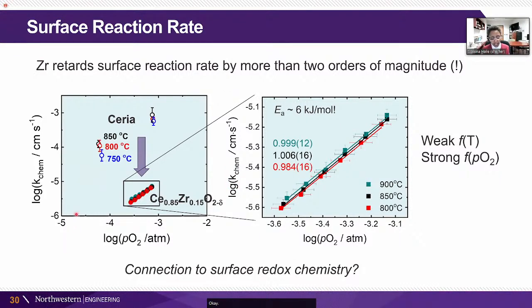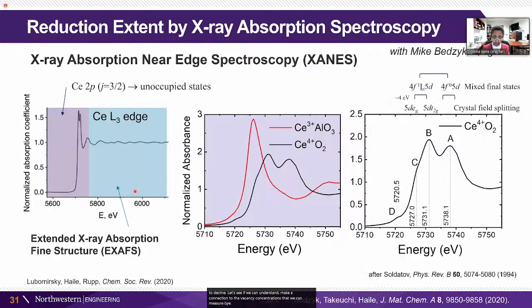Okay. So now we are going to connect to that surface redox chemistry, which I said, okay, all of this is macroscopic a little bit here. Zirconium, which we know introduces vacancies into the bulk, causes the surface reaction rate constant to decline. Let's see if we can make a connection to the vacancy concentrations that we can measure by more direct methods. And the method that we're using, as I said, is X-ray absorption spectroscopy.